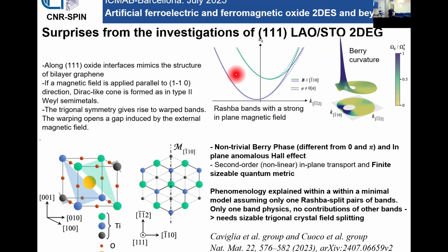In particular, if you consider a very simplified minimal model, with just a pair of Kramers bands, a single band picture with Rashba spin-orbit coupling, and you apply a very strong in-plane magnetic field, two Rashba split bands cross at finite momentum, which is well known. Due to the trigonal symmetry of the system, this gives rise to a gap along a particular direction of the Fermi surface. Due to that, the Berry curvature of the system is completely non-trivial. There are hot spots, which give rise to a non-trivial Berry phase.